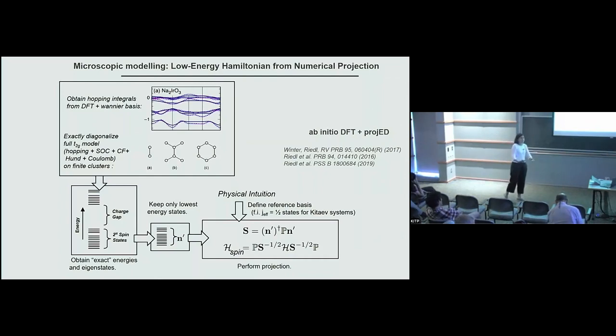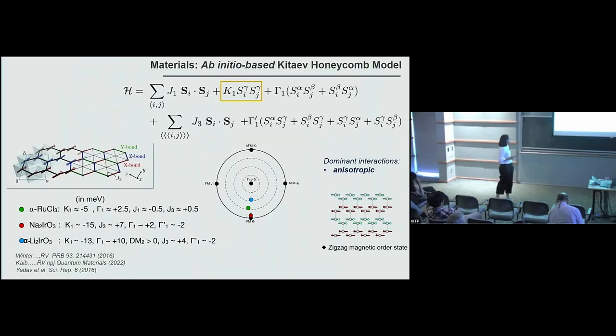And then the last step is, because we want a spin model, a low energy model, we choose the low energy states of these exact diagonalization results, and we project onto a spin space by defining a certain basis set. And this is the spin model that contains all the contributions that we know, so all the symmetries of the system, as well as all the possible distortions and hybridization processes. So by doing this, for instance, here what I'm showing is the minimal set of parameters that should be considered if we want to describe the properties of these materials.